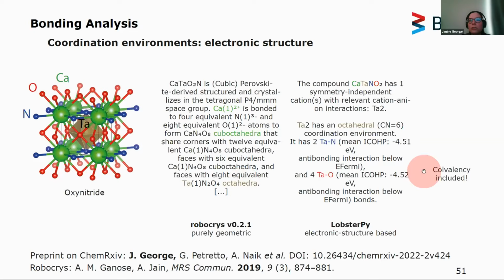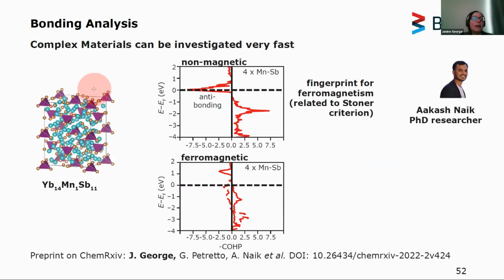So these purely geometric approaches are, for example, useful for diffusion properties, so lithium diffusion and things like that through materials. And I think these covalency-including approaches actually give us more information about what really contributes to the electronic structure of the material, which kinds of bonds are relevant here. And LobsterPy also allows us, of course, to look at really large structures in a very fast way. So for example, we looked at 14-1-11, which is a thermoelectric material. In this case, we looked actually at the magnetism. It's also ferromagnetic. And we looked at which bonds are actually responsible for the ferromagnetism in the compound. And this was really easy to analyze with LobsterPy.